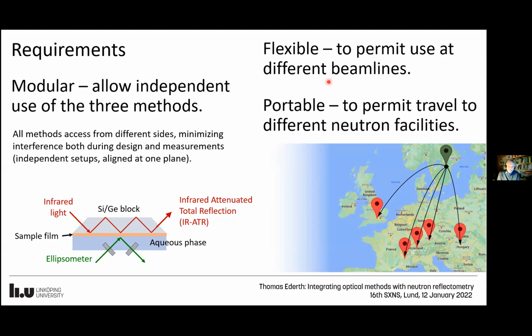well, the reason why this is fairly straightforward is that you can access the sample interface, the solid liquid interface, from different directions with each of these methods. So there is actually rather little physical interference. So in the figure, we have infrared light coming from one side, we have the ellipsometry probing from the other side, and there will be neutrons coming perpendicular to the image plane here.